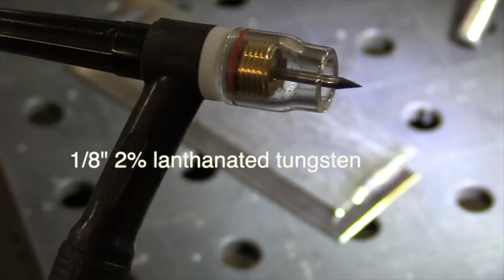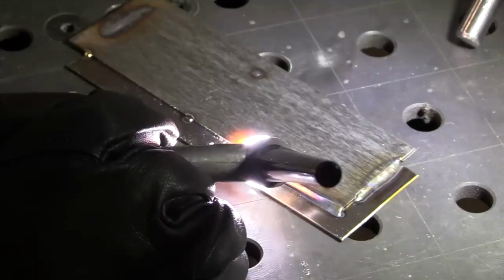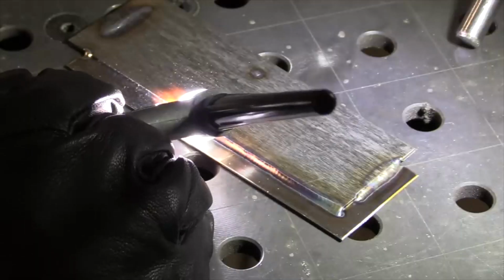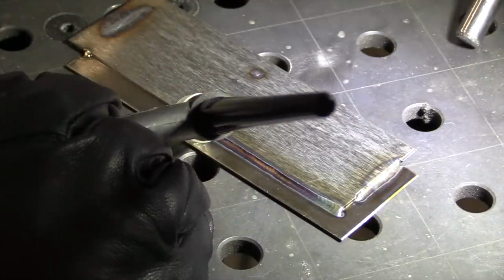There's a lot of overlap in the diameter of tungsten that will do a certain job. In this video I compared 1/8 to 040. This was only 16 gauge stainless, so I certainly didn't need to use a 1/8 diameter tungsten, but I compared it to an 040 and the results were very surprising. You would think that the 040 electrode would make a smaller weld at the same amperage as the 1/8, but again, the results were very surprising.